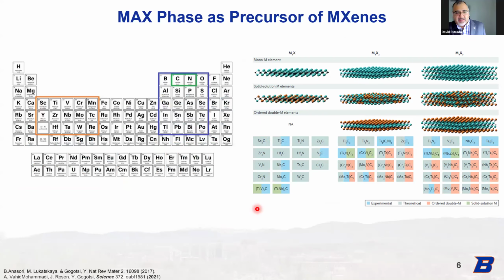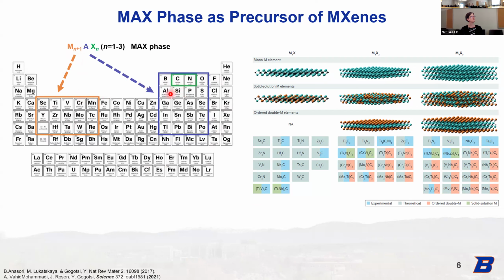For this application, the 2D material of choice that we decided to look at was done in collaboration with Yuri Gogotsi at Drexel University, and we're looking at MXenes as the active material. MXenes come from the MAX phase ceramics, where you have the formula M(n+1)AXn. M here is an early transition metal. A elements are typically shown here: silicon, aluminum, gallium seem to be some of the more common ones. And then X is typically a carbon or a nitrogen or a combination of the two.